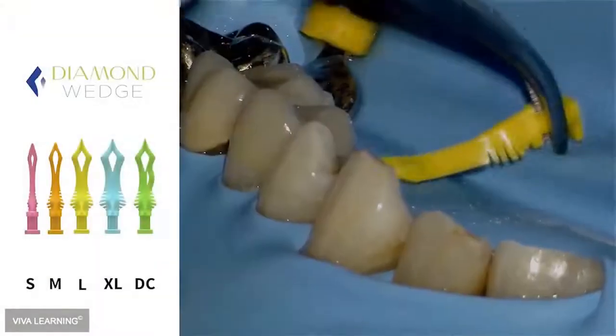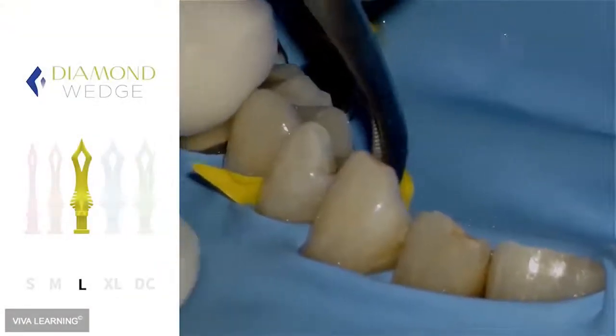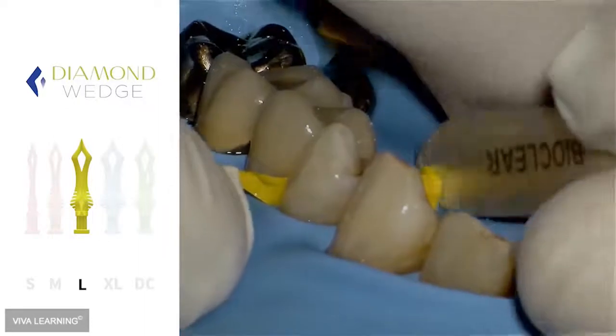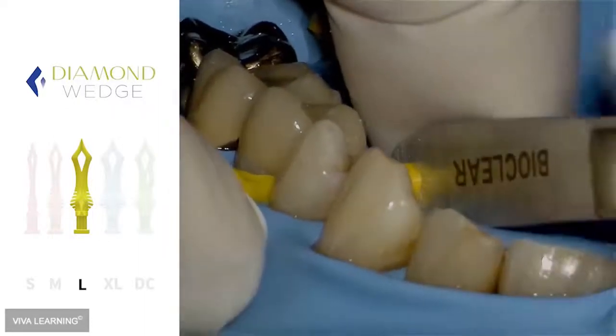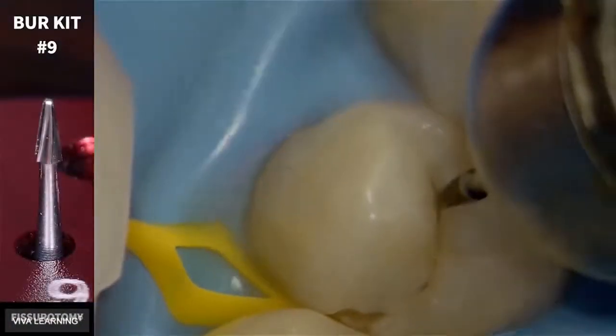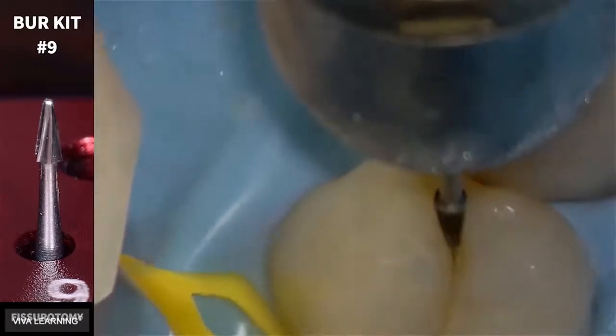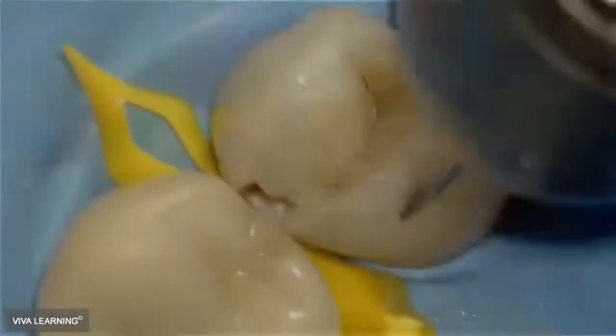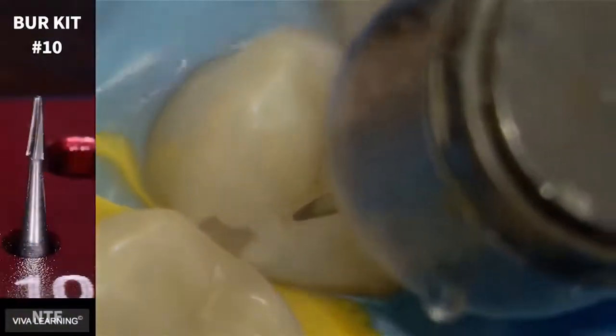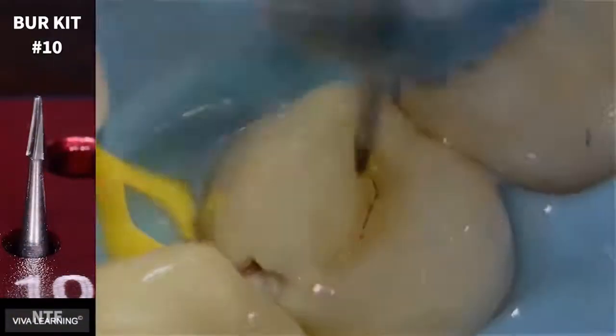We feel that the number one reason that composites are staining is because in the area that's the infinity edge, or what other people call flashing, you cannot remove biofilm with phosphoric acid. And so the composite never bonds, turns brown right away. So anyway, we did the blasting. This is a fissurotomy burr by SS White. We're going to create a bit of a radius cut here, try to create a compression joint. I'm leaning the burr laterally to create better stress mitigation. This is the NTF fissurotomy burr to get rid of those last little remnants of stain.